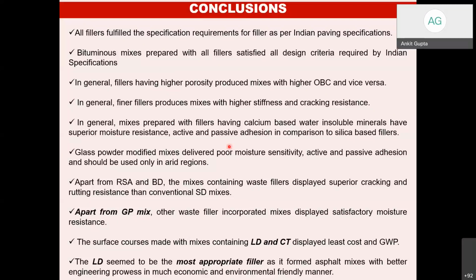In general, the mixes prepared with fillers having calcium-based, water-insoluble minerals have superior resistance in terms of all the performances. So calcium-based fillers are good as compared to silica-based fillers. Glass powder modified mixes are very poor in moisture sensitivity and in active and passive adhesion. It cannot be used, except where water is not a problem. So maybe in arid regions, the desert areas where water is not there, it can be used. So this again has certain implications on the field.